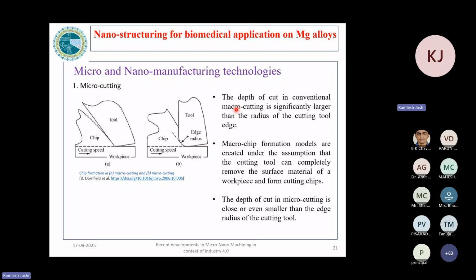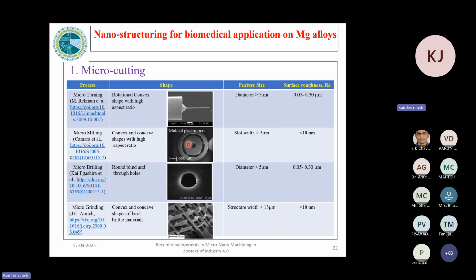The depth of cut in conventional macro machining is significantly larger than the radius of the cutting tool. So this is the radius of the cutting tool, and this depth is sufficiently large in conventional macro cutting, and the macro chip formation models are created with the assumption that the cutting tool can completely remove the surface material. But in micro cutting, the depth of cut is close to the radius of the cutting tool. So if we want a very small depth of cut, we can keep it in the range of the edge radius of the tool.